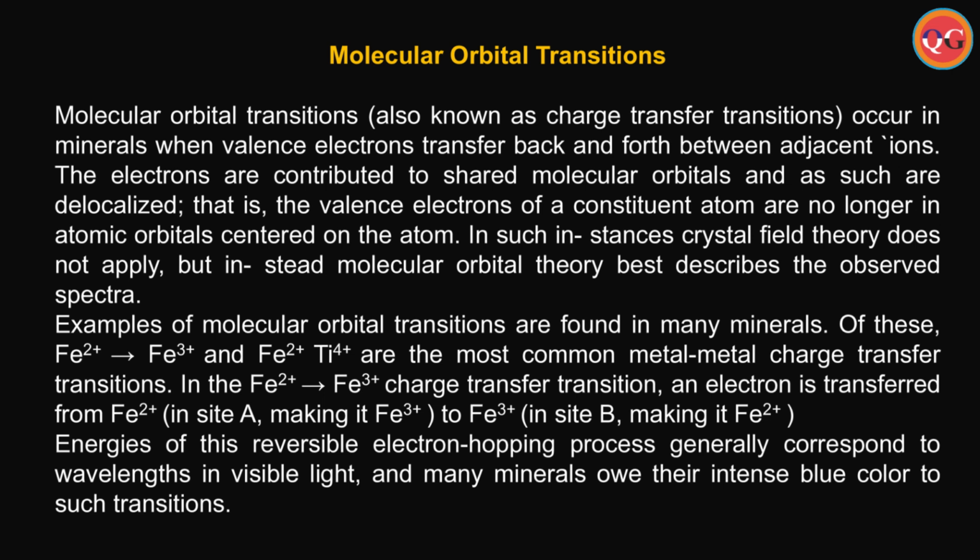Of these, Fe2+ to Fe3+ and Fe2+ to Ti4+ are the most common metal-metal charge transfer transitions. In the Fe2+ to Fe3+ charge transfer transition, an electron is transferred from Fe2+ in site A, making it Fe3+, to Fe3+ in site B, making it Fe2+. Energies of this reversible electron hopping process generally correspond to wavelengths in visible light, and many minerals owe their intense blue color to such transitions.